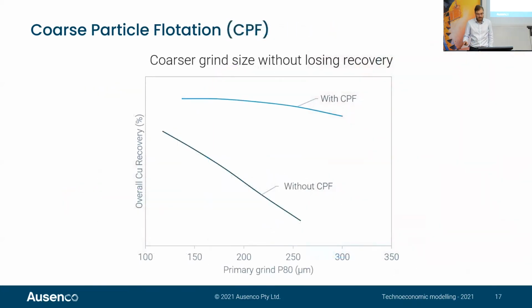So what benefit does that have? As I said, it allows you to coarsen the grind size without losing recovery. So you can see here some real data of what happens when you increase the primary grind without CPF, so conventional flotation systems. The recovery drops off dramatically. Whereas with coarse particle flotation, that recovery is extended out to much coarser sizes. And actually you start getting into constraints of the classification technology as to how coarse you can actually go in terms of the product from the milling circuit.